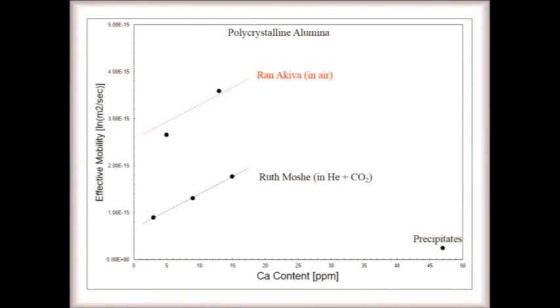More recent data. This is not published. This is what I showed you before for calcium. This is Ran Akiva. Ruth Moshe is a PhD student in my group now. And we've gone through and made some more data points. But we did these grain growth experiments in helium in a carbon furnace. Everything fits with the calcium concentration, but it goes significantly slower in the presence of carbon. Carbon plays a role in alumina.